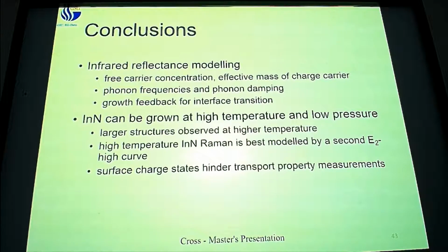Some conclusions. Infrared reflectance modeling can give me my free carrier concentration and effective mass of the charge carrier, or the charge carrier concentration. Those are not exclusive, unfortunately. I can find my phonon frequencies and phonon damping coefficients. I can find growth feedback for my interface perfection and interface transitions.